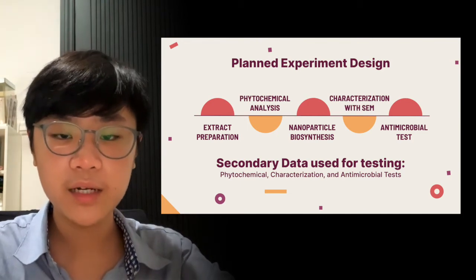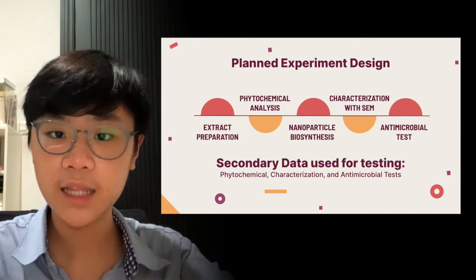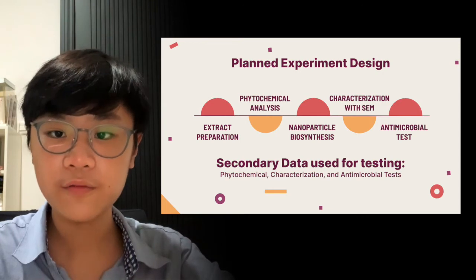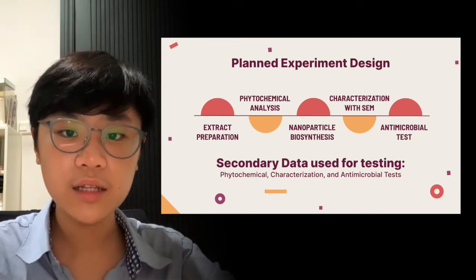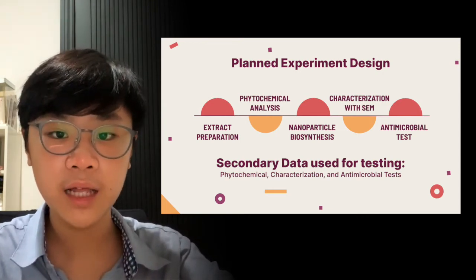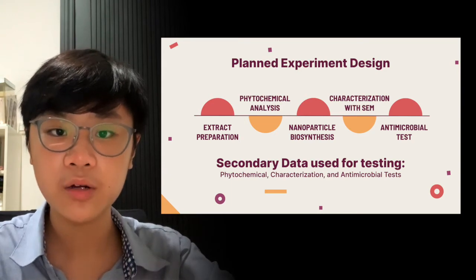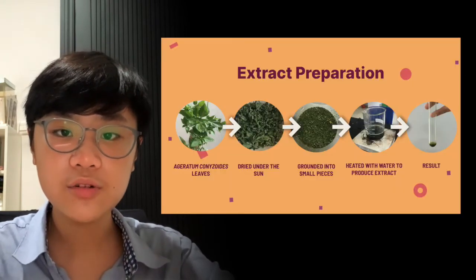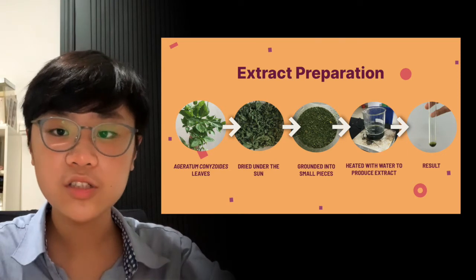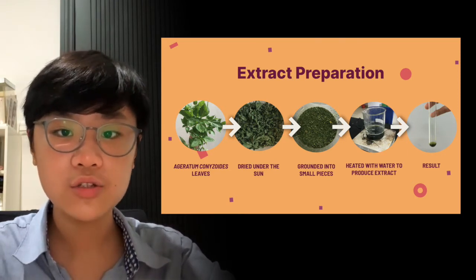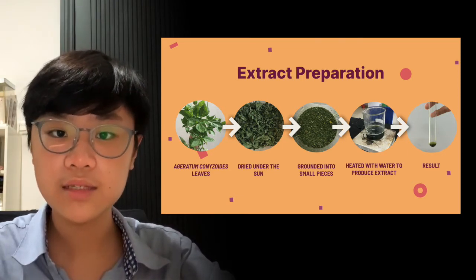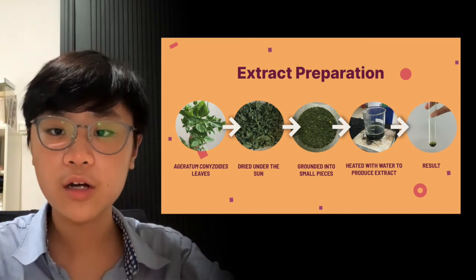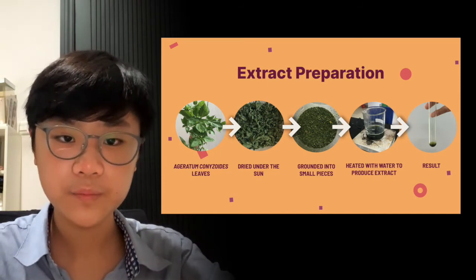Due to the pandemic and limited access to schools and labs, steps 2, 4, and 5 could not be conducted, so secondary data was used for the phytochemical analysis, characterization, and antimicrobial tests. The extract was prepared by first washing the fresh leaves to remove dirt, then drying, grinding into small pieces, and then the leaves were heated with water to produce the extract.